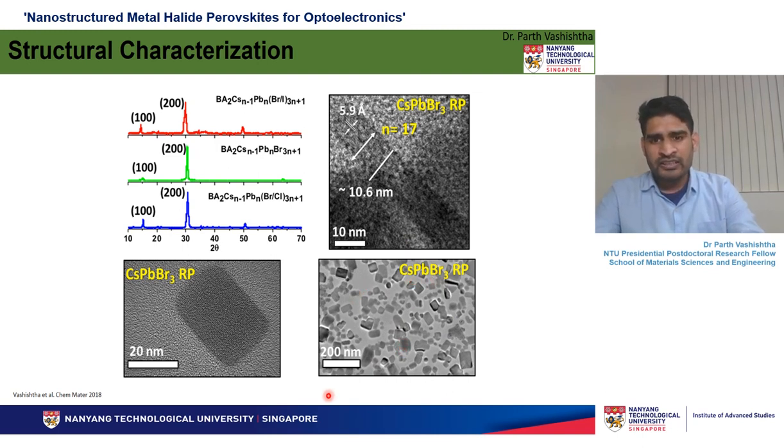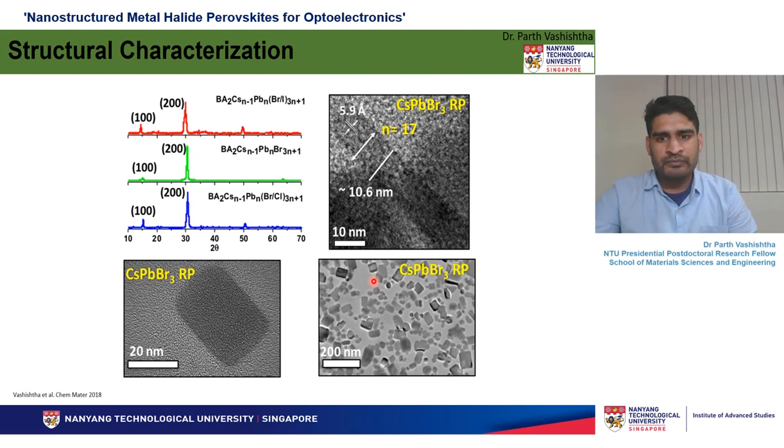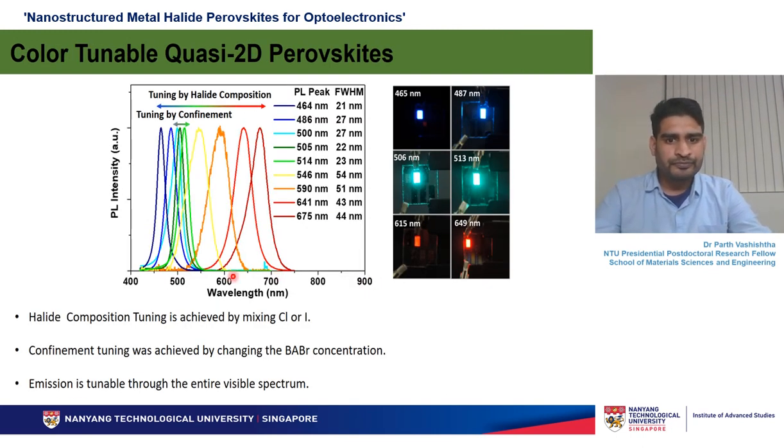But what we can see in the transmission electron microscopy, in the last image here, is that we are forming a lot of nanosheets, and some of them are front-facing like that, and some of them are side-facing like this. For the side-facing nanosheets, I could find some of them and calculate the number of monolayers, which is 17, and we found many of these. Some of them were 20, 24, 16, and we estimated the number of monolayers varied from 16 to 24.